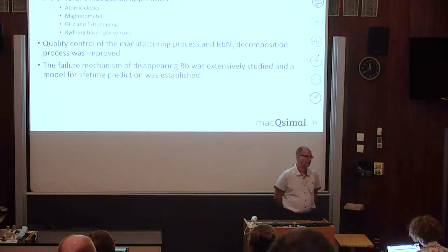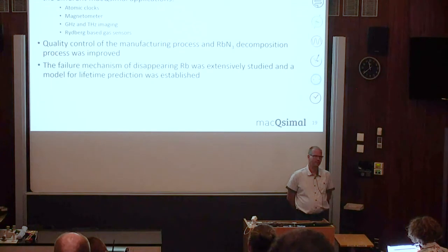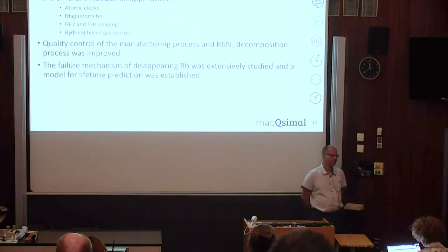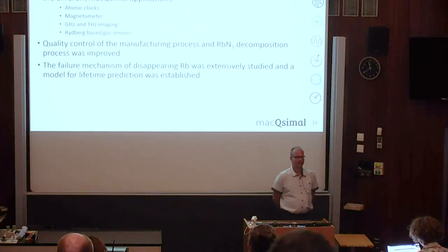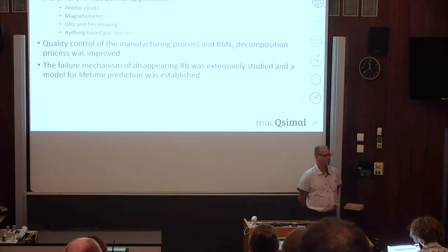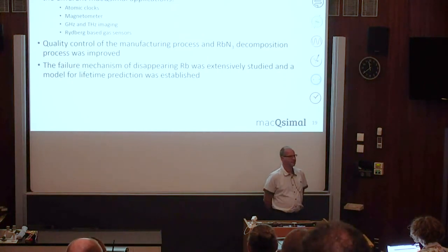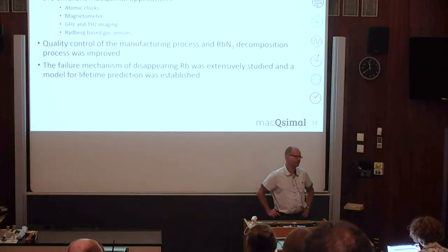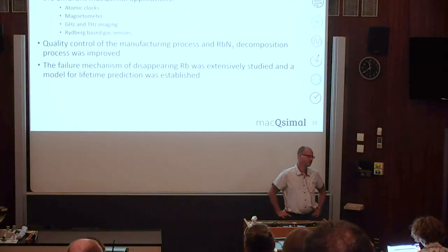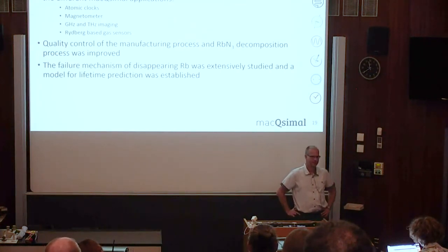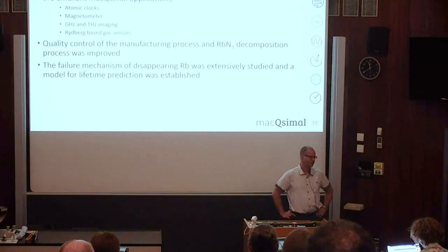We have also internal coatings. We have a coating, but which is more to avoid diffusion of the rubidium into the glass in particular. But it's clear that before the bonding, we extensively heat the preform with the rubidium azide already inside to 320 degrees, 350 degrees for a long time, so that we can evacuate all the trace atoms, molecules that are sitting on the surfaces. But we have an anodic bond, which is leak tight in principle, but of course, leak tight doesn't mean anything. There's still exchange of, for example, helium. Yeah, I know you can measure this, but it's very, very low.